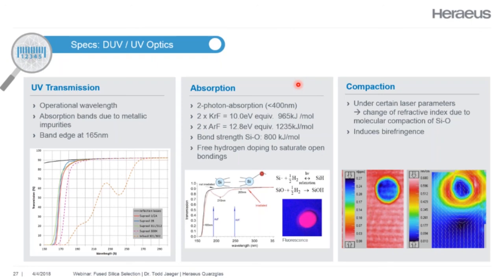Now, compaction is really a special case. It really only happens under certain laser parameters, but it's a molecular compaction of the actual SiO bond. This causes a localized change in the refractive index, which can induce birefringence. If it's a topic you're interested in, please contact us and we can provide some additional information. So what's the solution then?